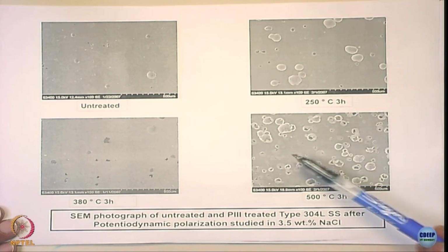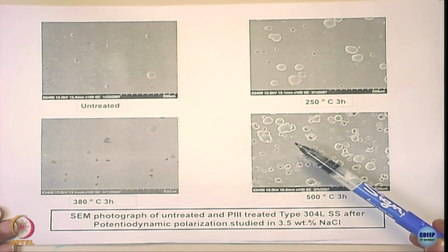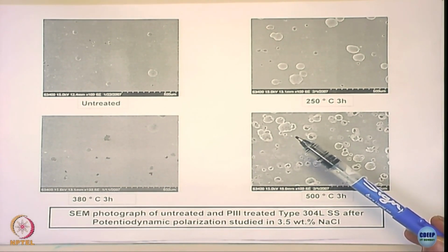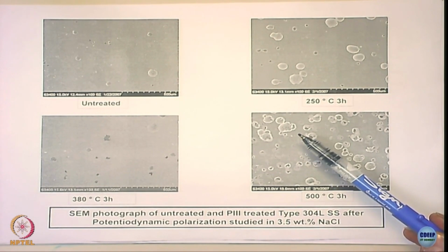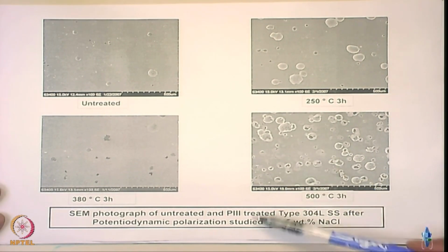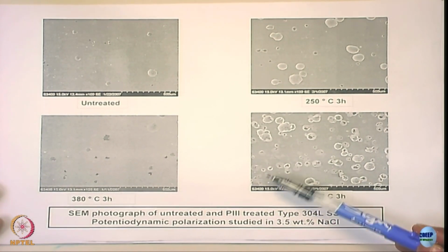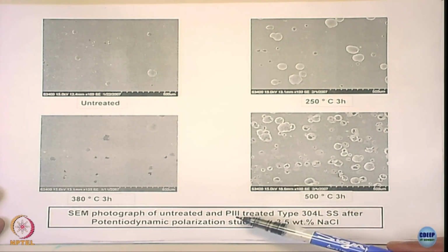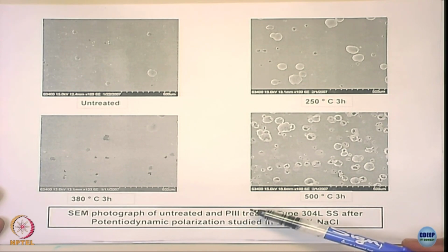Essentially this is a PhD work, okay, wherein they converted the surface so that it can have higher pitting resistance and higher passivation. In that case they have added nitrogen by plasma source ion implantation, also called the plasma immersion ion implantation technique, okay.